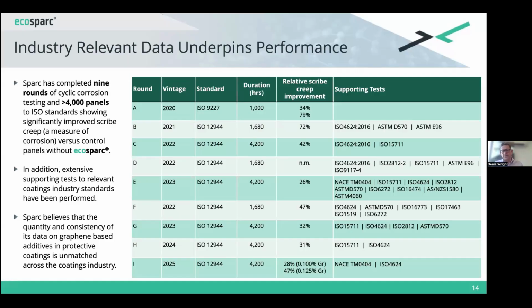And on the right-hand side of the screen there, you can see the other ISO tests that we do that are supporting data. Some of it's mandrel testing, some of it's other scribe creep like adhesion work, some of it's crack resistance testing. There's a whole stack of material that we generate so that we understand what's going on with whatever we're working with. We think we've got a significant body of data that we can fall back on and talk to, as you can see from this very short presentation, and we're happy to extrapolate out and expand out on that as we need to, and no problems at all.